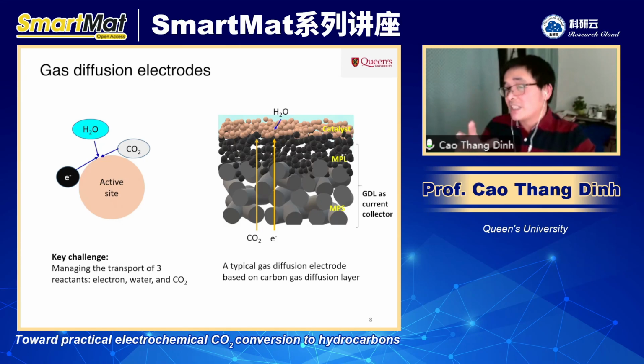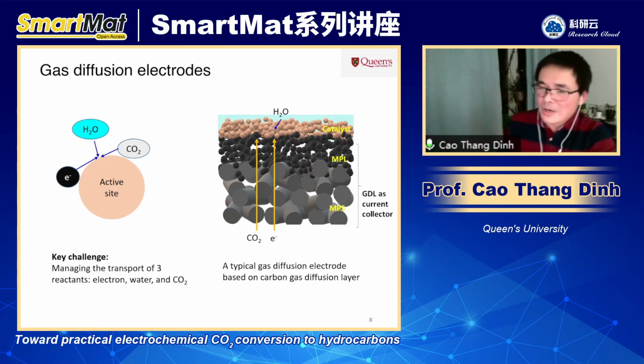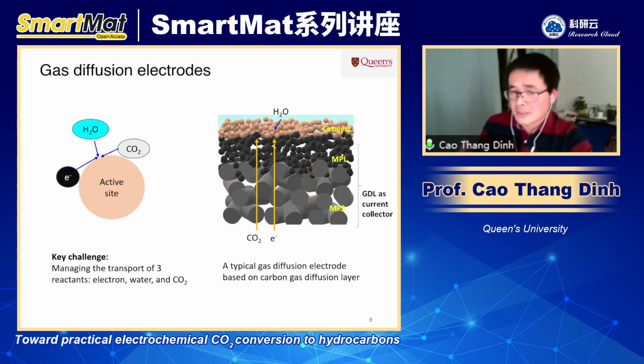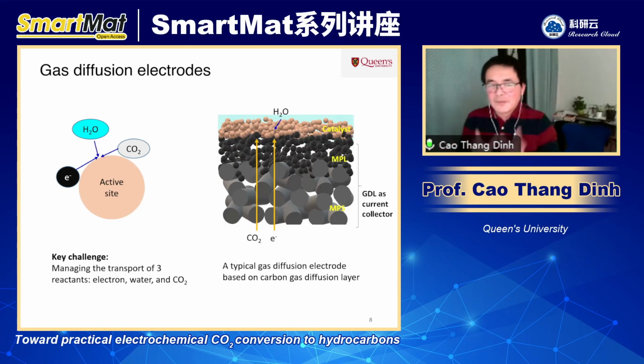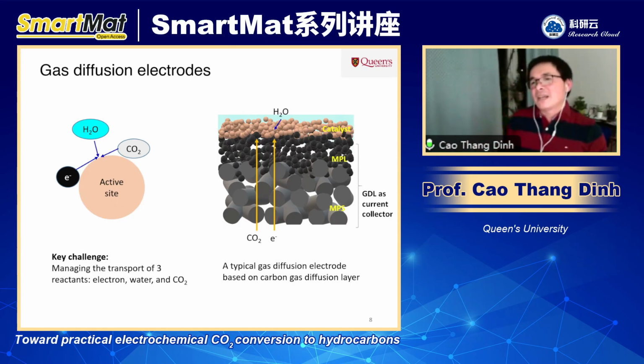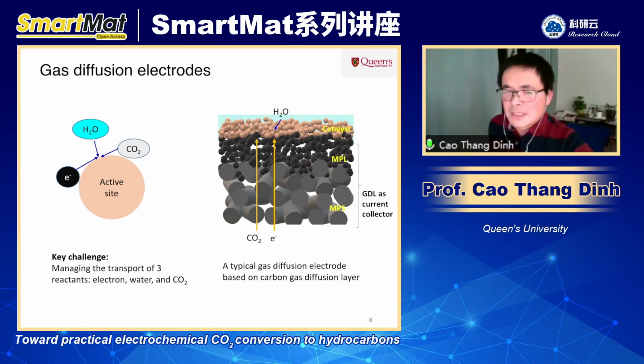And then the electron needs to be in an electrically conductive substrate, right? So in principle, you will need a solid that is conductive, and then you need CO2, and then you need water. So that is often a three-phase interface, bringing them together. And it is quite challenging to bring three different components in three different phases together. But it's not something unusual, because over 50 to 100 years ago, fuel cell technology had already identified the way to overcome that. And the way that we overcome this problem is using the gas diffusion layer.